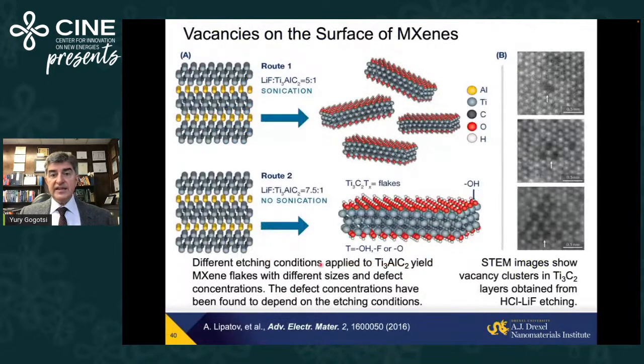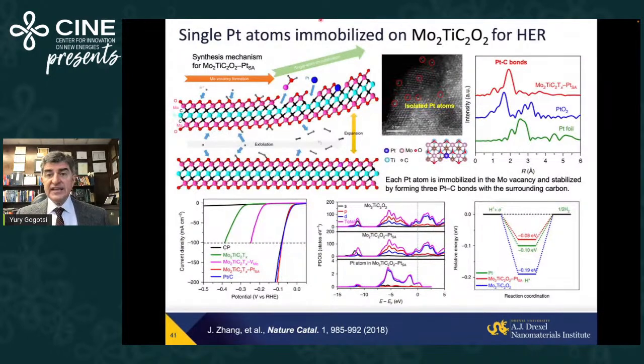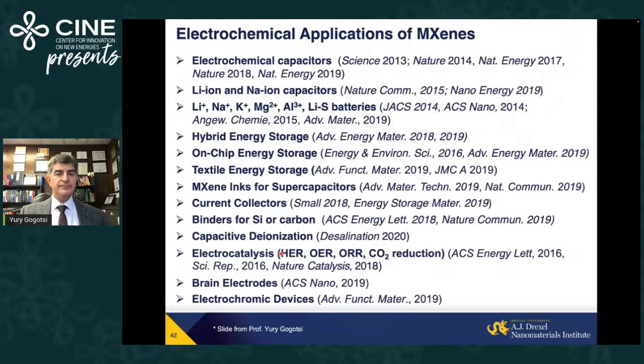However, if we incorporate single atoms of platinum into point defects, basically replacing some of the transition metal atoms in the surface of MXene, we can get material with single atom platinum with a very small amount of platinum added, but performance now matching platinum on carbon with a much larger loading of platinum. So again, you can design with these materials, and this is the key advantage of them.